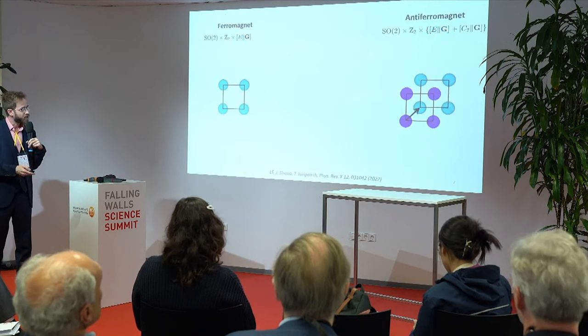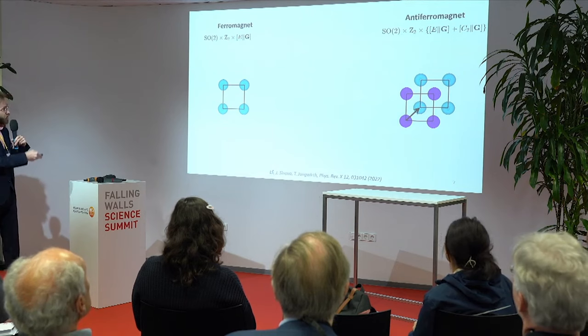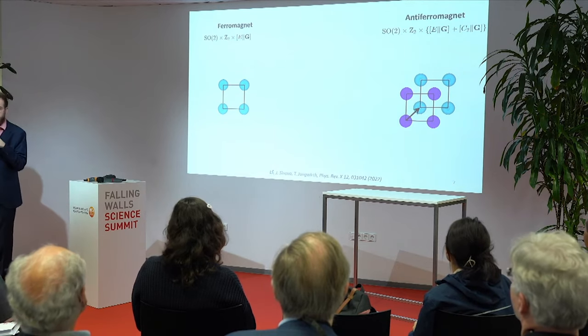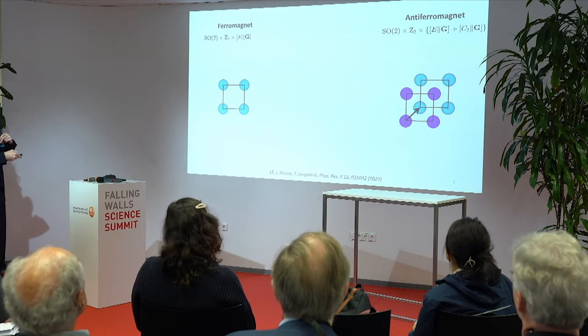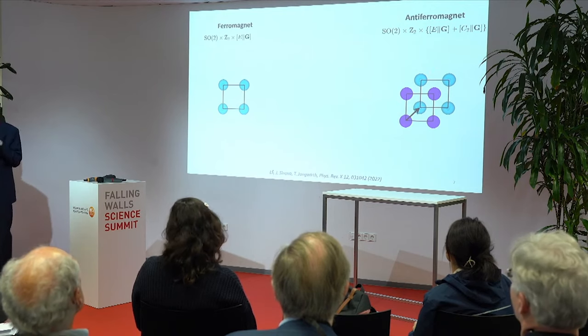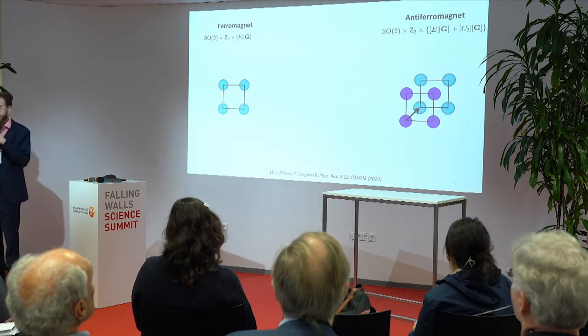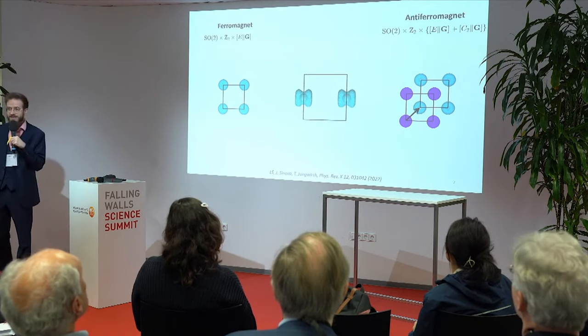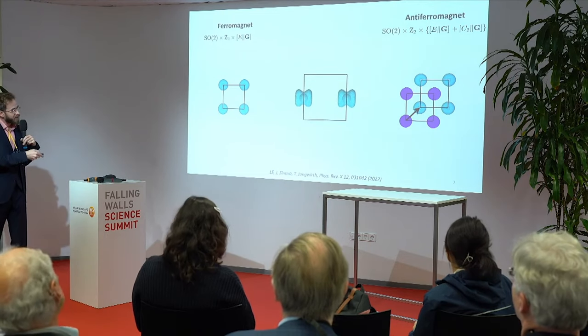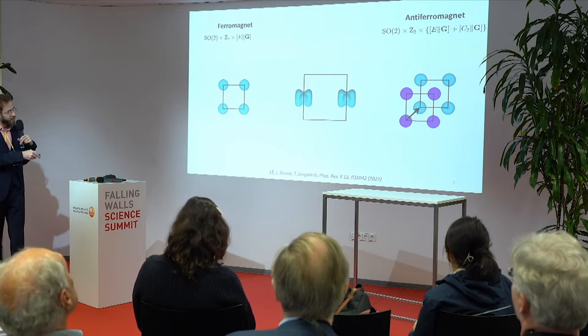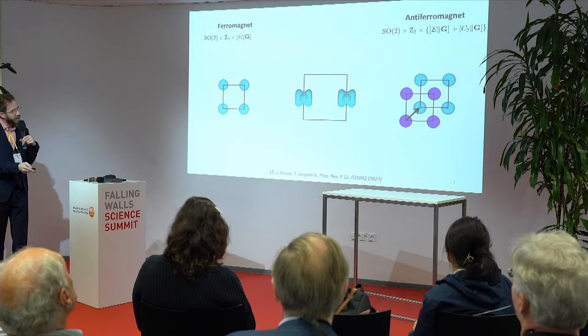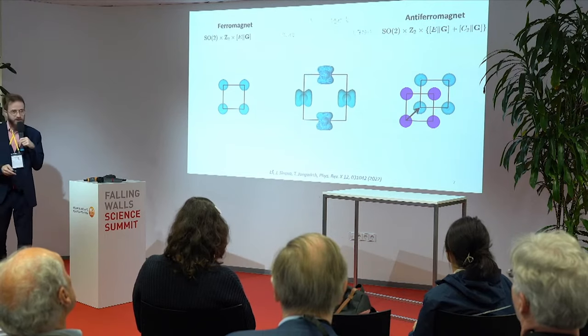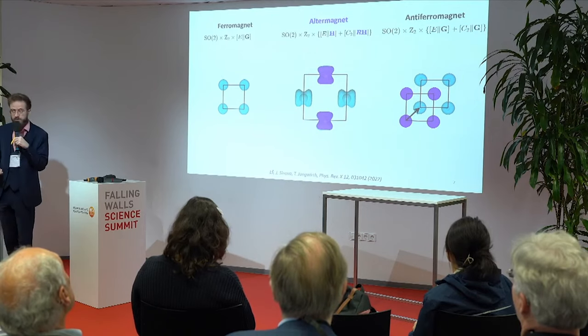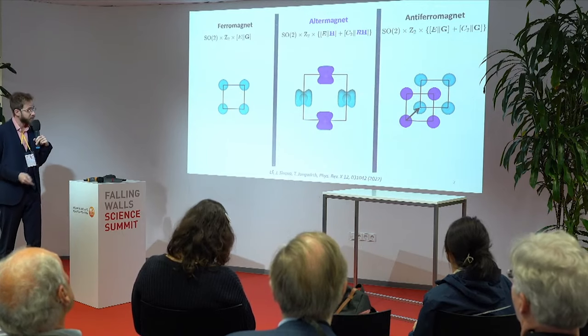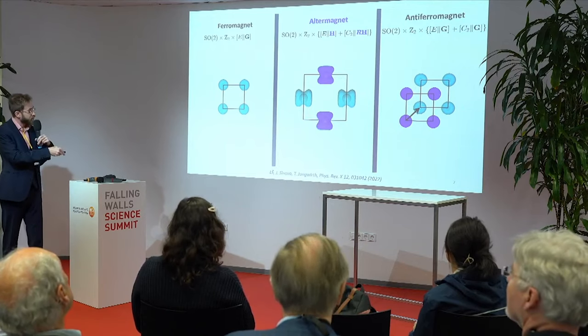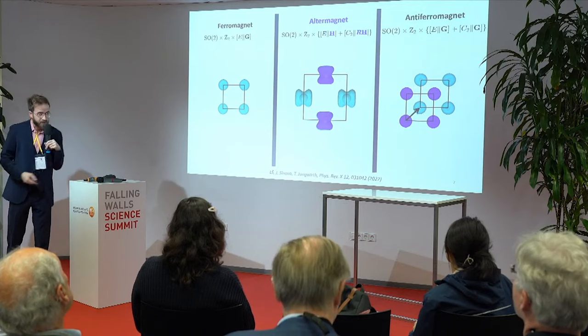So we tried to do this classification, and we were able to reconstruct the two conventional magnetic phases. I will not go into the details of the magnetic symmetries, but you can see that this mathematics is very different for them. Basically, in ferromagnets, you have one spin sublattice. In antiferromagnets, you have two spin sublattices related by translation, for instance. And finally, there exists yet a third possibility where the single spin sublattice is breaking the symmetry of the crystal, because you see that this has a lower symmetry than the square. And then, when we rotate such a sublattice and we change its spin, it remains a symmetry. So we have now again this 90 degree rotation in the crystal space combined with a 180 degree rotation in spin space. And it turns out that these are equally likely possibilities mathematically, which are separated distinctly by these walls.